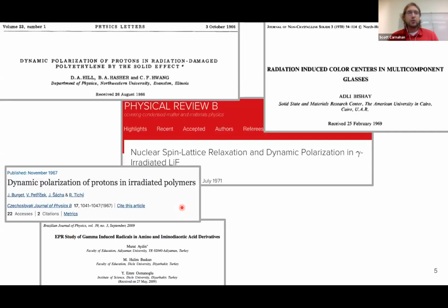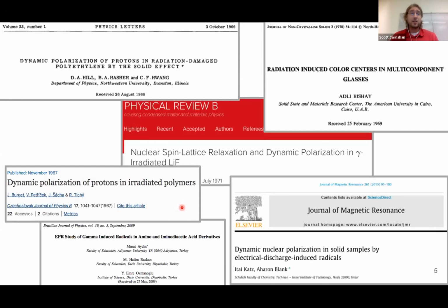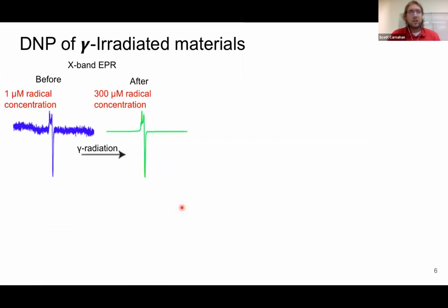So using gamma radiation or neutron radiation to create radicals for DNP is not necessarily a new idea. Some of the earliest DNP experiments used these radiation damaged samples. So our idea was to take that initial idea and bring it to high field NMR using MAS, as well as doing it at more moderate temperatures, because a lot of these were done at low field, static, and at ultra low temperatures.